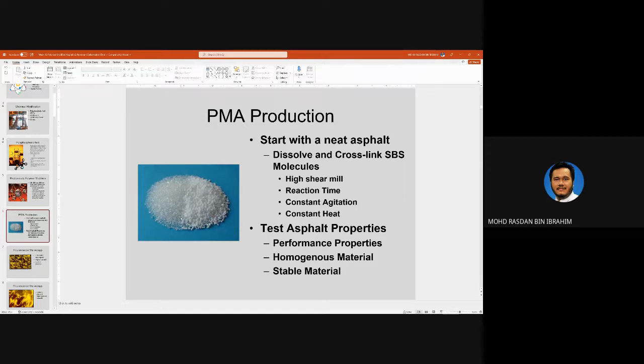How do you actually use the propeller? If you are using a propeller mixer, is it constant agitation or constant heat? The heat must be consistent. Then we test the asphalt properties, we test for performance properties, the homogeneity and stability. They are more or less related, homogeneous and stable. Stable means that when you have mixed the polymer inside the bitumen, heated it up and left it for some time, the particles of the polymer do not settle too much to the bottom of the barrel. If the tendency to separate between the polymer and the bitumen is high, it means that you cannot mix the bitumen and store it.